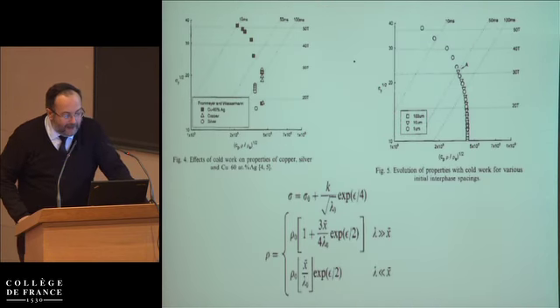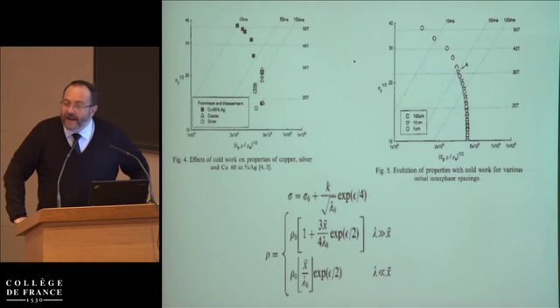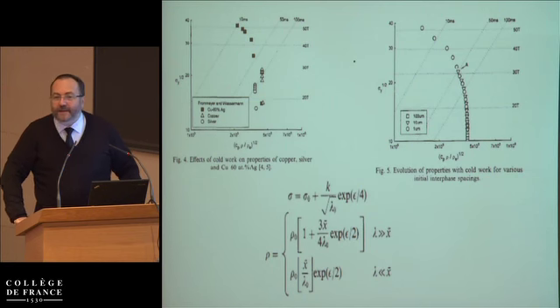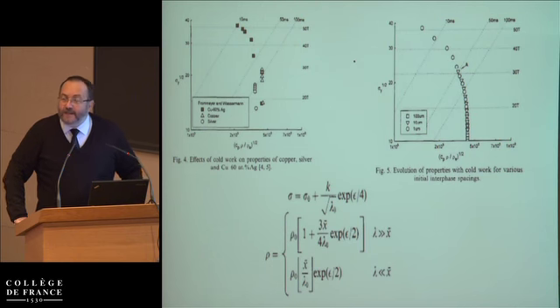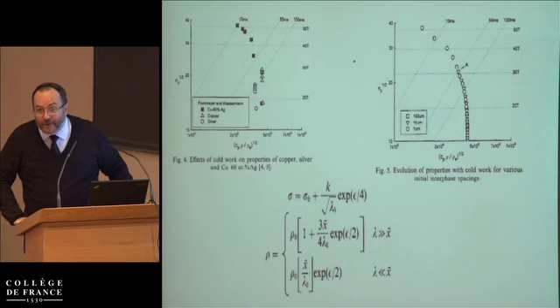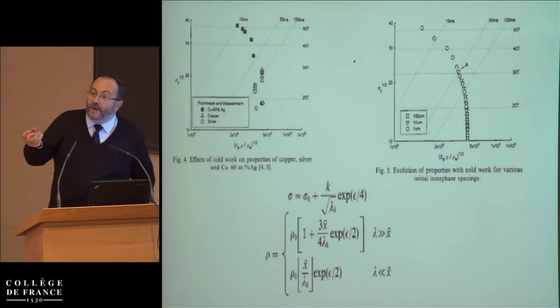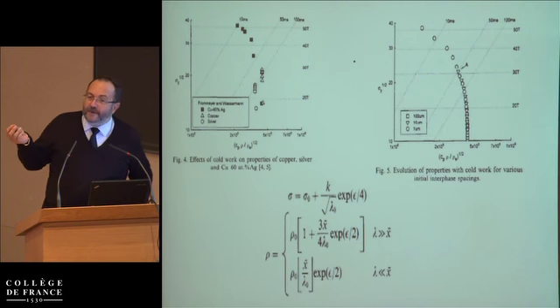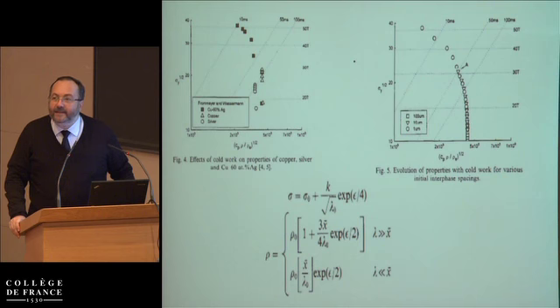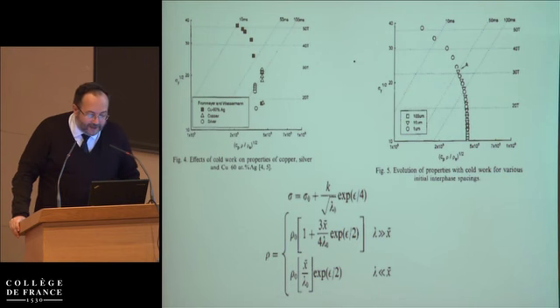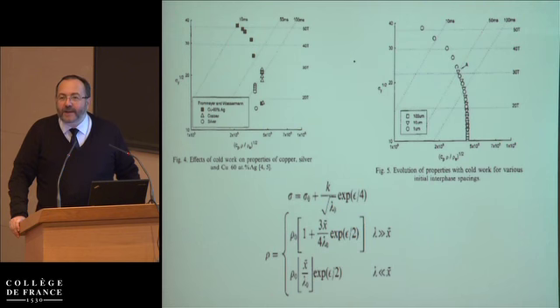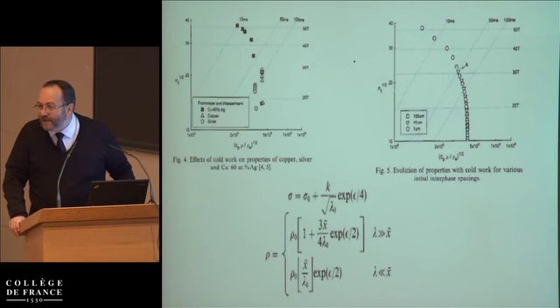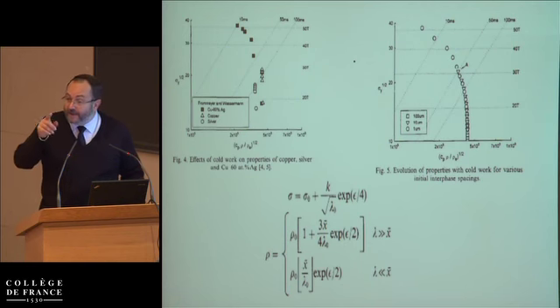Now, interestingly, you can have a direct relation between the yield stress and the spacing between the niobium fibers inside the copper matrix. And this spacing is, of course, related to the amount of strain that you have imposed on your composite. So you have on one side a process parameter, which is a strain, which is going to control the strength of the material, simply because the obstacles are preventing the dislocations from moving. So that's the meaning of the first equation. And the second set of equations is the relation between the electrical resistivity of the material and the distance between the fibers, because the fibers are playing the role of scatterers for the electrons.